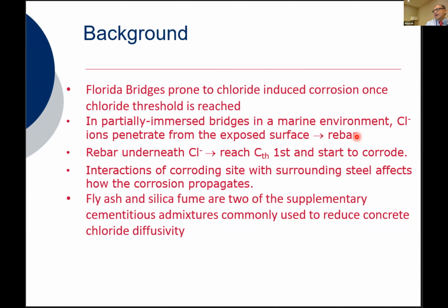In this particular project, we focus on binary samples that were prepared with fly ash and others with silica fume. These are two commonly used supplementary cementitious materials in Florida. It's a little harder now to get fly ash, but at the time that these samples were prepared, it was being used quite a bit.